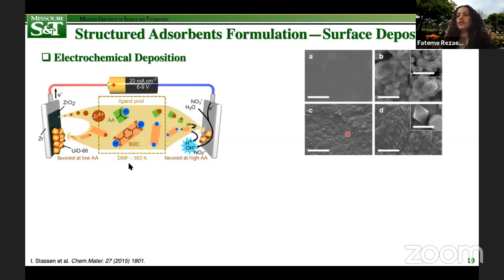Now, these SEM images here show pristine zirconium foil and zirconium foil substrate after 30 minutes of MOF anodic deposition in the presence of acetic acid with varied molarities. The MOF deposited channels were then used in a custom-built vapor sampling device for adsorption of toluene as a model VOC compound, which was efficient in trapping and concentrating toluene vapor.